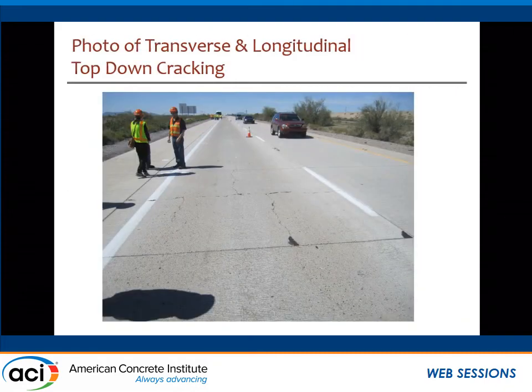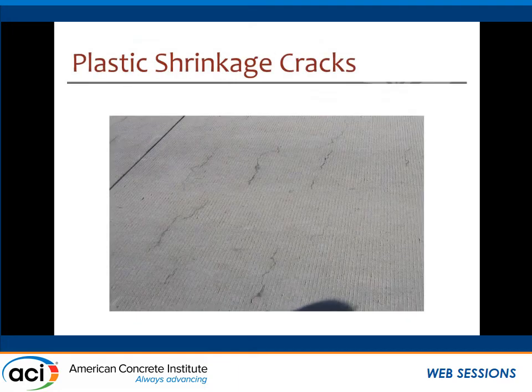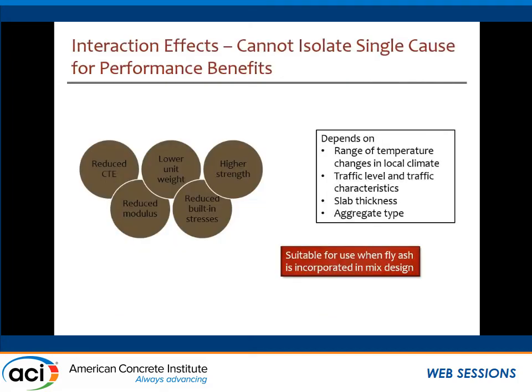Here's another picture that shows the development of top-down cracking, both in the longitudinal and the transverse direction. So this curling can occur in both directions, and you can have failures both in the longitudinal and transverse directions. These are some pictures of plastic shrinkage cracks. These appear shortly after construction, and a lot of times contractors have to go in and replace slabs before the pavement has even been open to traffic. So these are the type of failures you have a good potential to control with the use of internal curing.